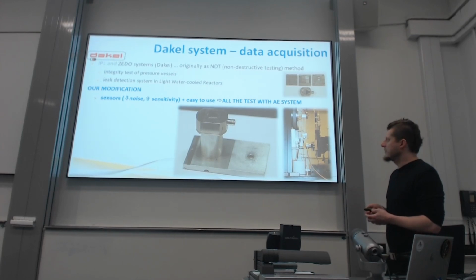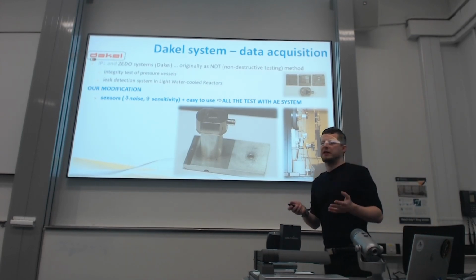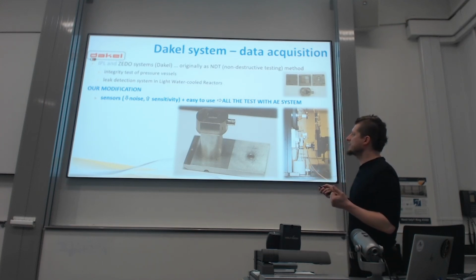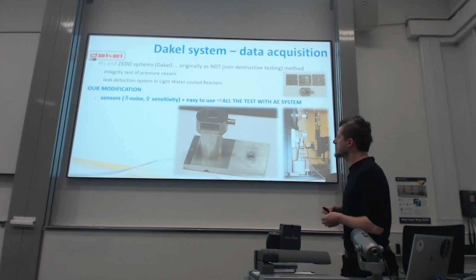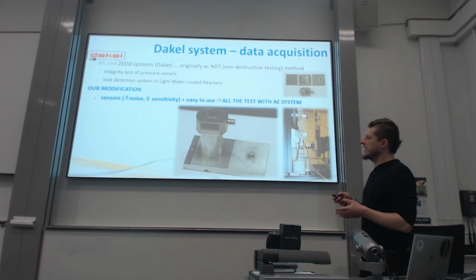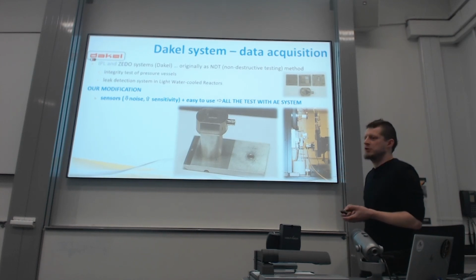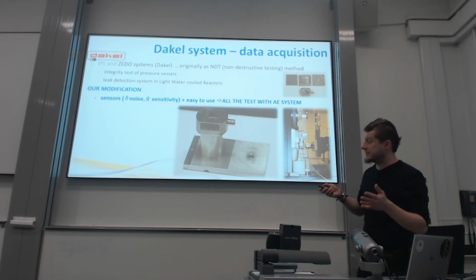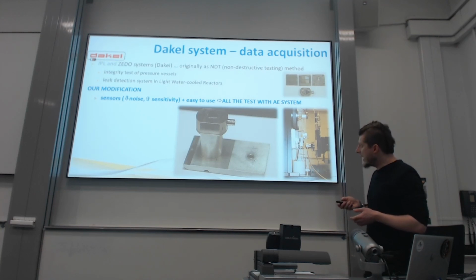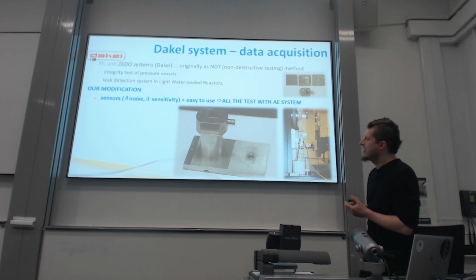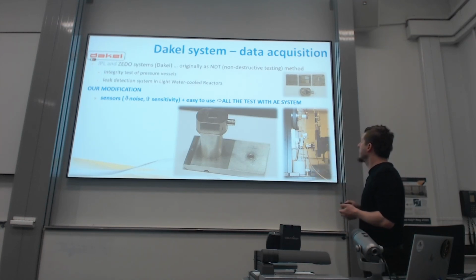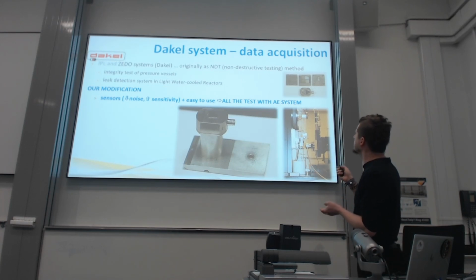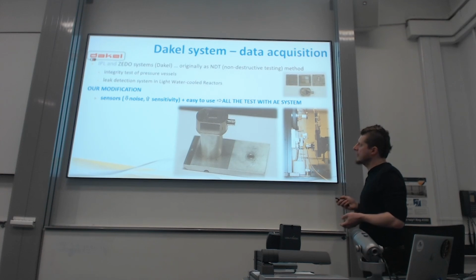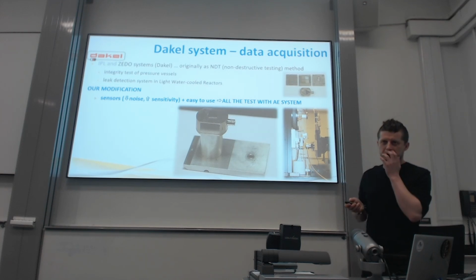If you want to analyze the acoustic emission during some local mechanical tests, you generally have two approaches. You attach the sensor close to the object, close to the sample, with some glue or something, or you can attach the acoustic sensor to the indenter, because you want to be as close as possible to the source of acoustic emission. Because the thing is that the acoustic signal can be dampened during the process, through many interfaces between the source and the sensor. But we have this product which is quite handy, because it's a normal holder and not much bigger, or even smaller than the standard Micro Materials holder. It's a little thicker, and we are using it quite often. We are using it nearly on every measurement as a standard tool.